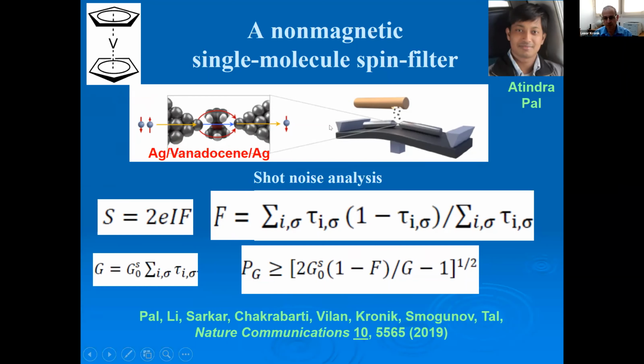There is nothing to interact magnetically or antiferromagnetically, etc. So how would you go about measuring spin polarization if the lead is not magnetic? You can't do magnetic resistance. So what Oren did instead, which is I think quite clever, is to rely on shot noise analysis.